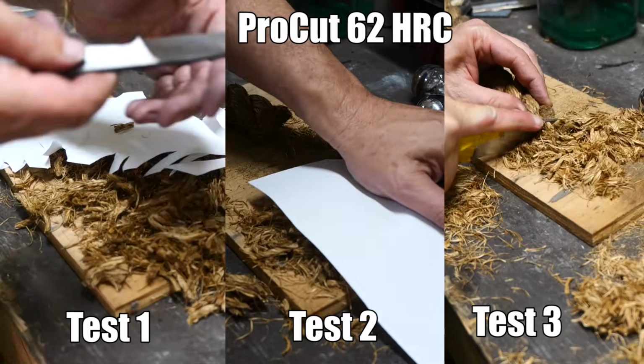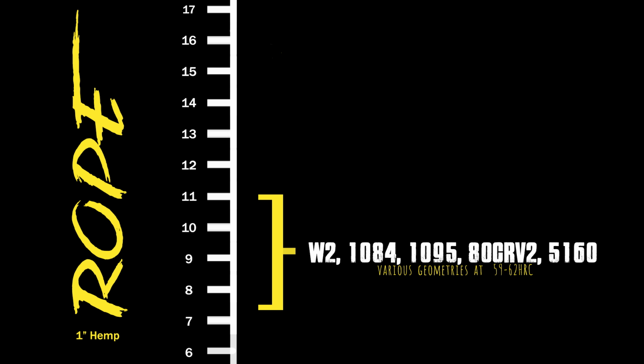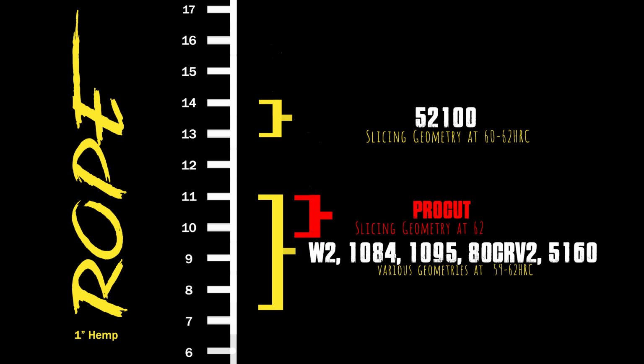With various blade geometries and HRCs of anywhere from 59 to 62, W2 steel, 1084, 1095, 80CrV2, and the 5160 knives I've tested cut this rope anywhere from about 7.5 to 11 times. I got 5160 to go through it 12 times once, and 52100 is up here at 13 at an HRC of 60 and 14 at an HRC of 62. And that is where I was hoping ProCut would fall, somewhere in the 15 to 16 range maybe.